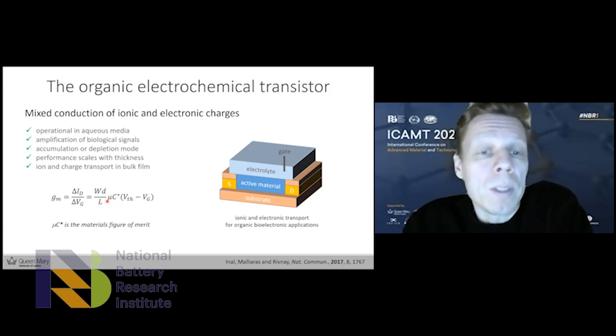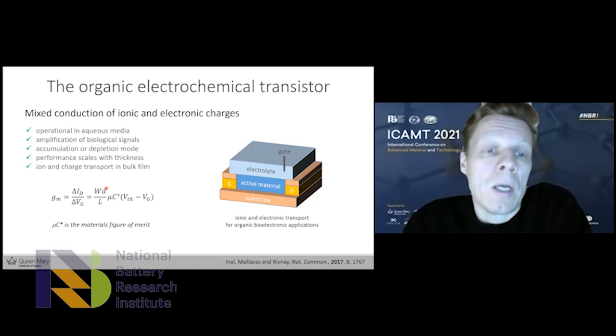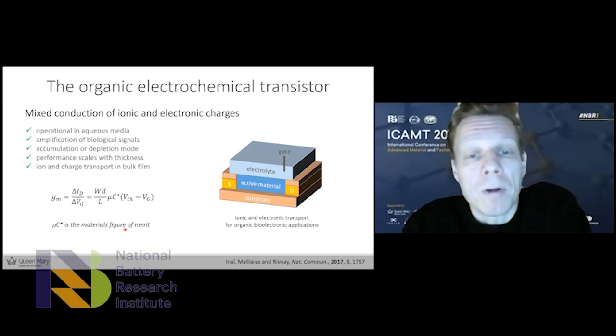as the electronic mobility, and C star, the effective capacitance. Those 2 parameters are the only ones that are related to the material, to the active material. The other ones are related to the configuration of the device and to the way we operate it in terms of bias. So only mu and C star are materials dependent. So we think about the mu C star product as the materials figure of merit, one we can understand in terms of new materials that we develop.